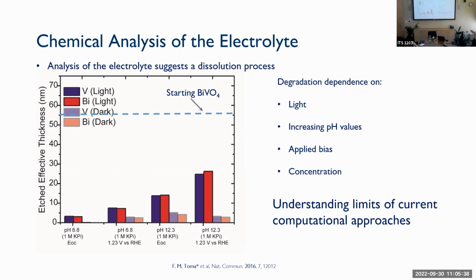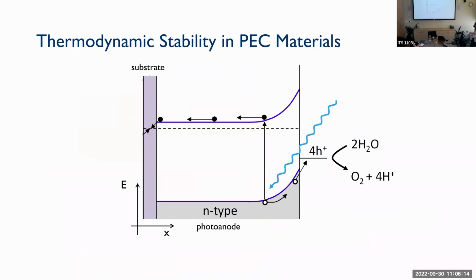So the degradation depends on light. Shine light on the sample, it will degrade faster. On increasing pH values, that was obvious from the SEM images that I showed you earlier. On applied bias, the higher the bias, the operating voltage of the device, the faster the degradation. And also the concentration of the electrolyte, which I haven't told you, but it's actually an important parameter to ensure conductivity of a solution. You want the electrolyte to be highly concentrated, but the high concentration is actually damaging the material. In order to understand corrosion better, you can use computational approaches to this.